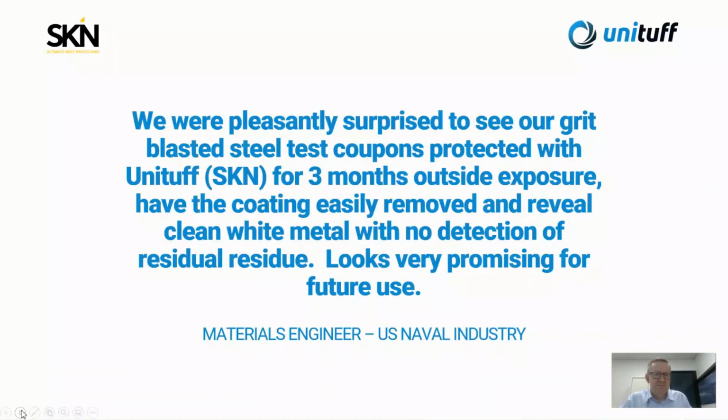This was just a recent naval industry contractor that we got a written testimonial back from. I'll let you read it, but I'll read it out to you as well. We were pleasantly surprised to see our grit blasted steel test coupons protected with Unituff (SKN) for 3 months outside exposure, having the coating easily removed and reveal clean white metal with no detection of residual residue. Looks very promising for future use. So that was from a different industry than oil and gas. I know we've got a few different industries on the webinar today, but this is certainly a very exposed condition, as you guys are in that marine environment. So very positive feedback.